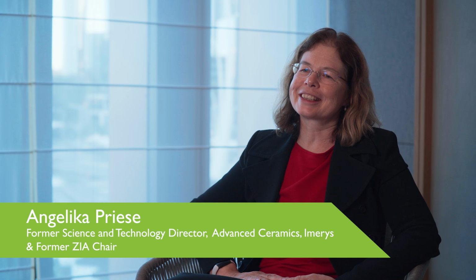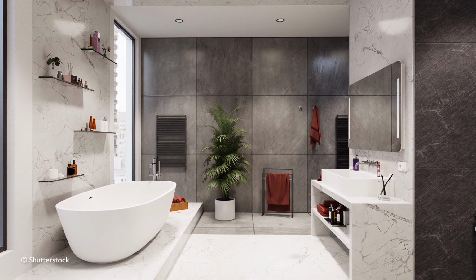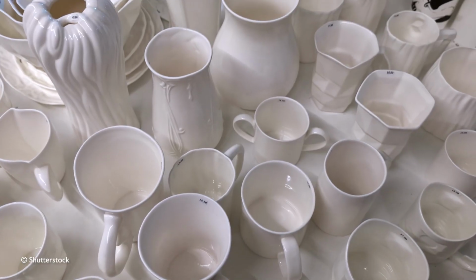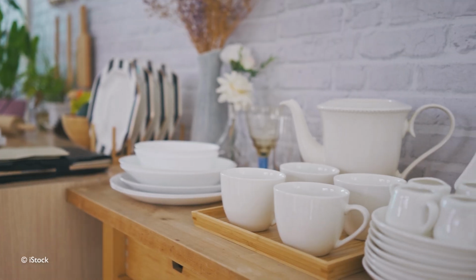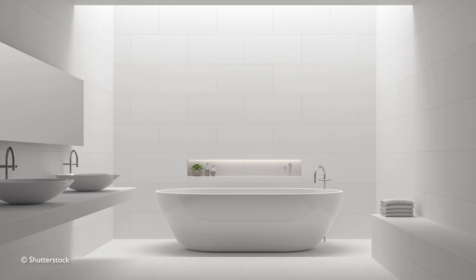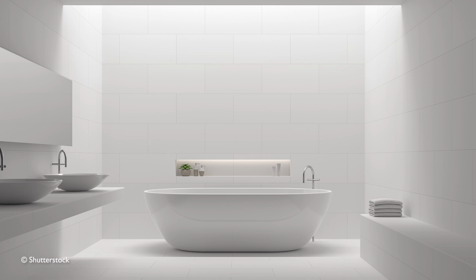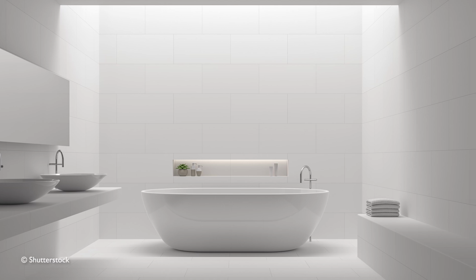So the main use of zircon sand is the use as opacifiers in ceramic tiles and sanitaryware and also tableware. Almost 50% of zircon is used in that application. Zirconium silicate has a very high refractive index. That means it scatters the light very easily, and therefore it can be used as an opacifying agent in ceramic applications, such as in tableware or in sanitaryware and in tiles. It gives a very high brightness level and a very good whiteness level.